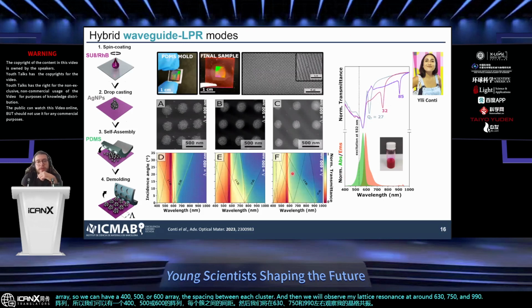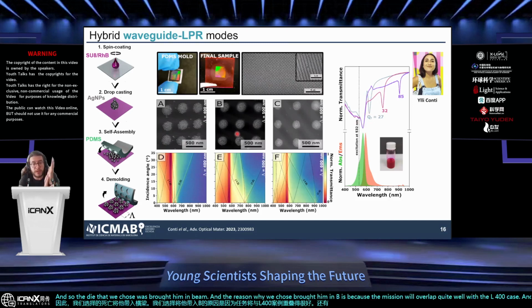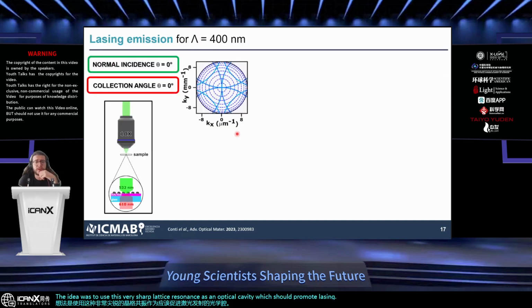And so the dye that we chose was rhodamine B, and the reason why we chose rhodamine B is because the emission will overlap quite well with the L400 case. And the idea was to use this very sharp lattice resonance as an optical cavity, which should promote lasing. So what you see here in the slide is a K-plot of the system. And so we have a high concentration of states right here in the normal direction.